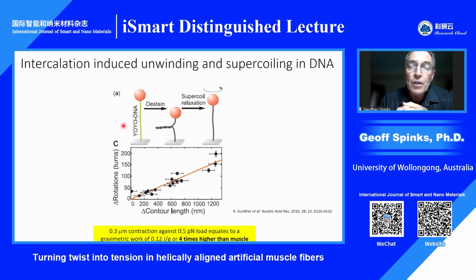Now, when that happens, if the magnetic bead is constrained to stop rotation, then the end-to-end length of the DNA strand decreases and a supercoil forms. If the magnetic bead is free to move, then the staining produces a rotation. Now, we might say staining, intercalation, maybe that's just another way of saying swelling and deswelling as we stain and destain. So perhaps there's an analog between what's happening here at the single molecule level and what we see in our torsional actuators, because we certainly know in torsional actuators, if we have a twisted fiber that we can swell, it will want to untwist.